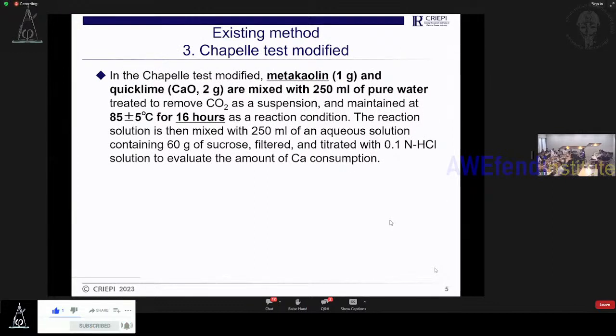The third one is the modified Chapelle test. It was used in France, I remember. They use metakaolin in concrete admixtures, which is not fly ash. Metakaolin has much higher reactivity than fly ash. In that case, they mix 1 gram of metakaolin and 2 grams of quick lime, meaning CaO, free lime, into 250 milliliters of pure water. The reacting condition is 85 centigrade, kept for 16 hours. And we estimate the consumption rate of the calcium ion.